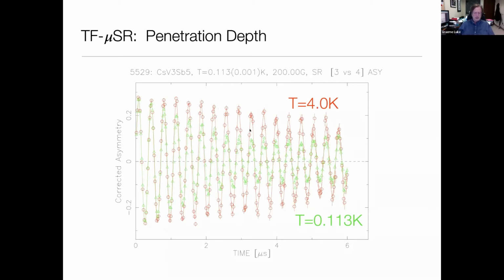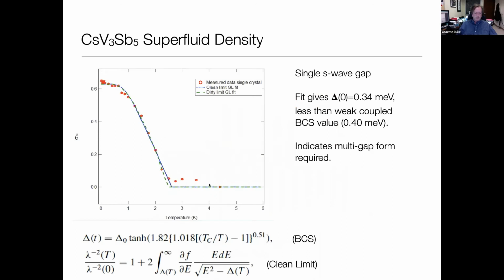Of course, there's a slight negative frequency shift due to the Meissner effect, which tends to lower the average internal field. But in this geometry with a large demagnetizing effect, that's not a very large effect. And now we can look at the temperature dependence of the damping rate of this signal and learn about the pairing state. So here the data points are the relaxation rate as a function of temperature. You can see here's TC of about 2.5 Kelvin.